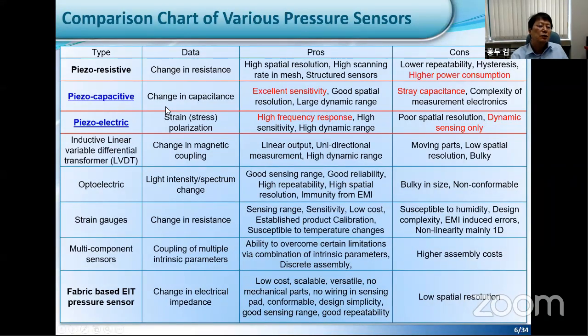There are some good and bad things about these two materials. In the case of piezocapacitive, it has very excellent sensitivity and good spatial resolution. The bad thing is that it has some inherent stray capacitance. In the case of piezoelectric, it responds very quickly, less than 0.1 hertz, or I mean a 10 hertz response time. Also, the bad thing about this piezoelectric material is that it only senses dynamic pressure. That means if you press on something, then you can pick up the signal.